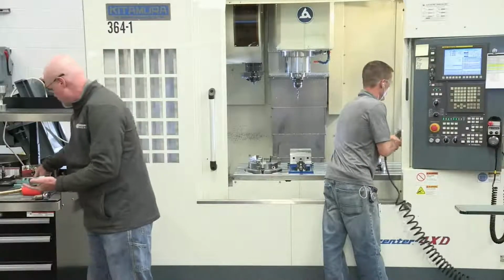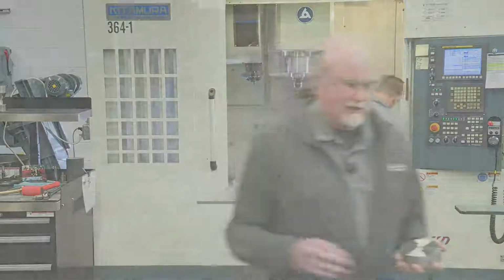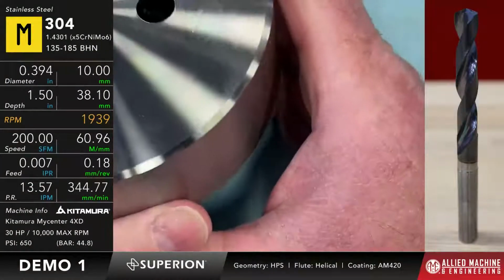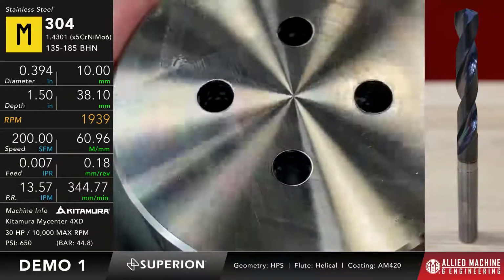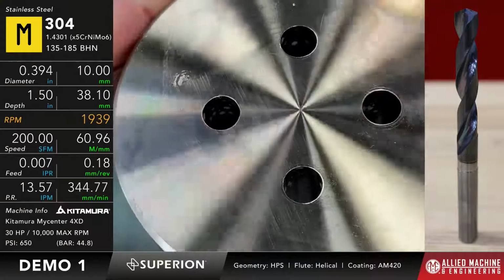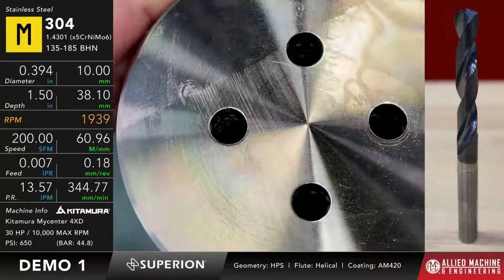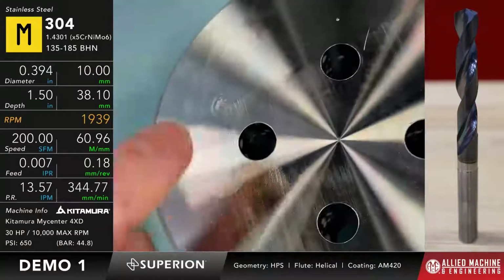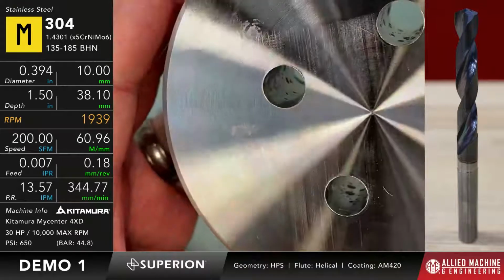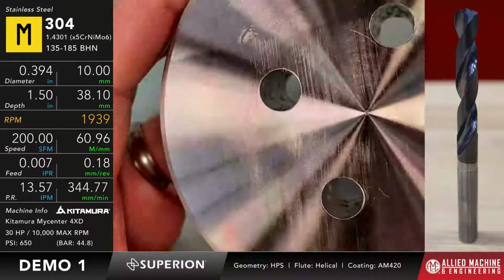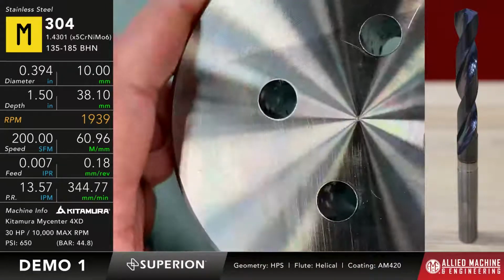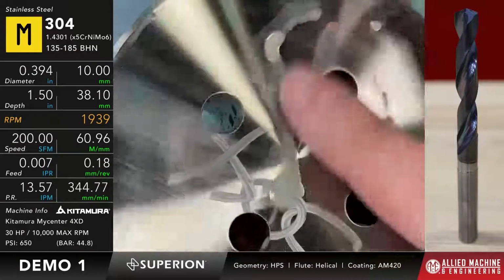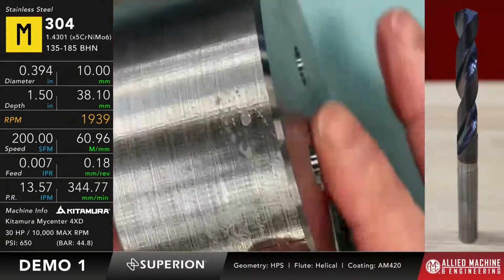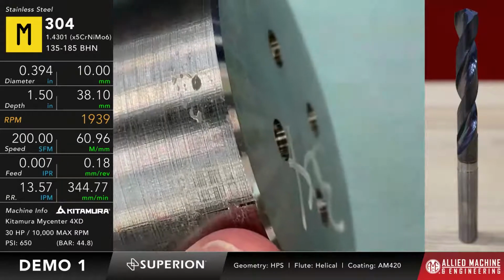So while Dave's getting that situated, let me grab the piece of 304 stainless. We'll take a look at that underneath the camera here. So here we go. As soon as I figured out how to center this, there we go. This was the first batch of holes that we ran. This was the one that we did with the, was that the HPS? Yes. Is that right? For the first one? There we go. So once again, 10 millimeter hole. Let me see if I can get this tilted around so you can see the quality of the finish. It looks pretty good. There's not a lot of deep gouges or anything like that. And based on the chip form that we saw, not really a big surprise. I'm going to flip it over here. The exit burr on it is quite small. Kind of tilted up here so you can see. There's a little bit of an exit burr, but you can barely even feel it. So that came out really, really well.